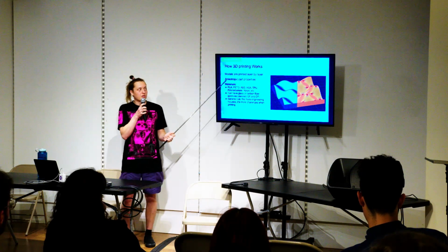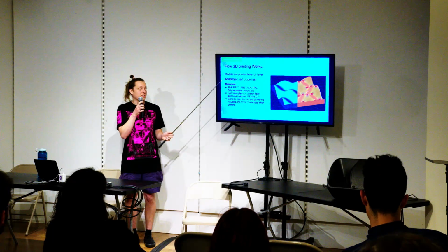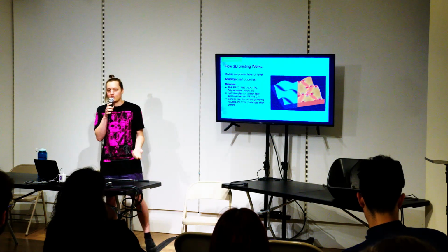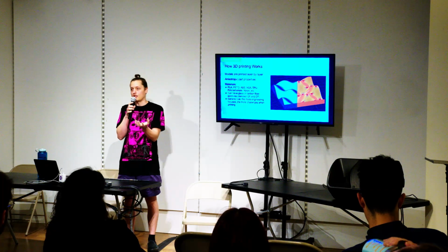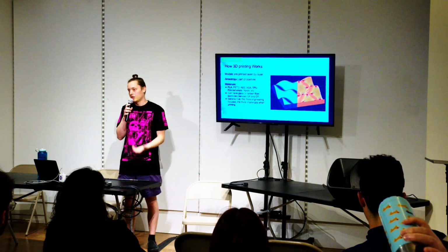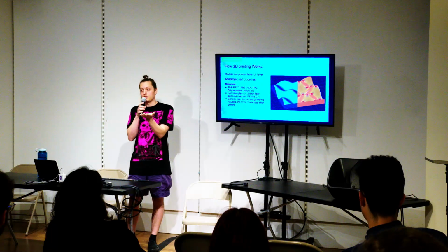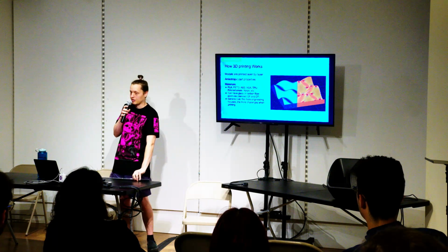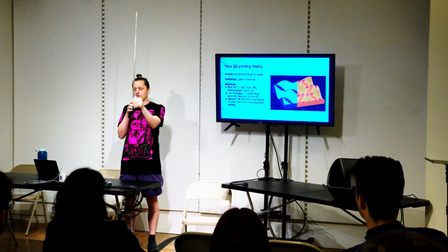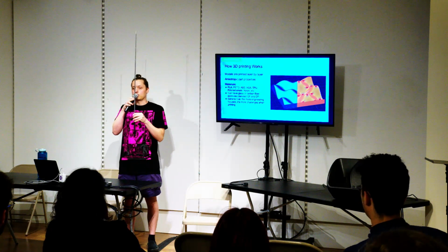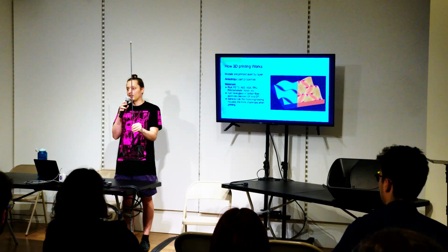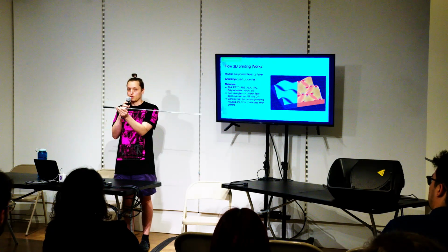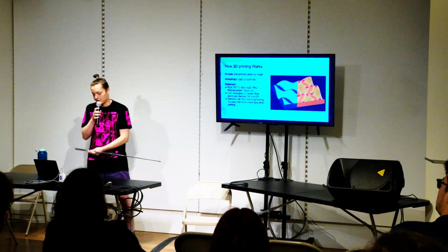And then you also run into a big thing with 3D prints, is they have anisotropic part properties, which basically just means that the strength and other things are not the same in all directions. So prints are much more likely to have a failure along the layer lines. So if you have something long like this, if you printed it vertically so that the layer lines go across, it's much more likely that that part will break than if it was printed horizontally with the layer lines running through the part. So you get a much stronger part in this orientation.